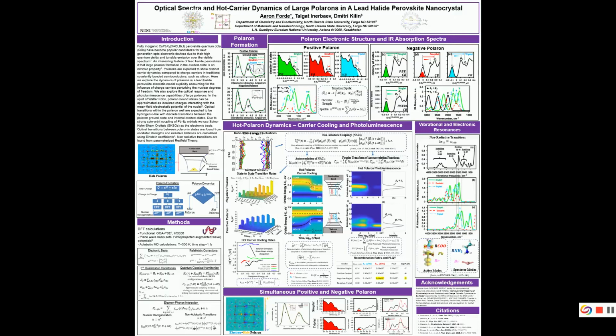And so that's the methodology out of the way. Looking at the structural characteristics of the polarons, we use the radial distribution functions for each system, for the positive and the negative. In this, we only look at the coordination between lead and bromines. That's illustrated with this picture here. A is a lead to bromine bond distance, whereas B is a bromine to bromine coordination distance across the lattice. And for both models, we see specific characteristics of nuclear reorganization.